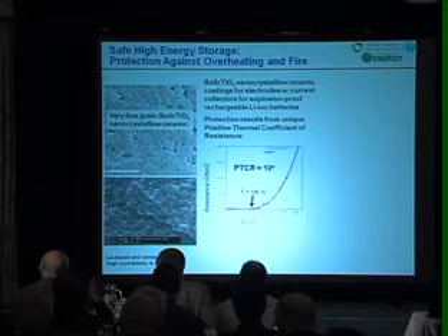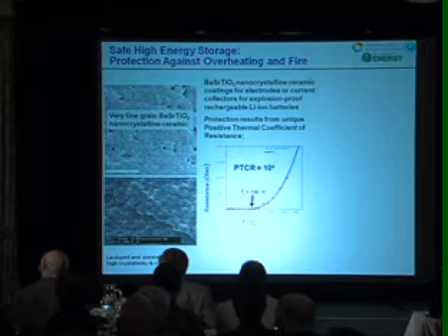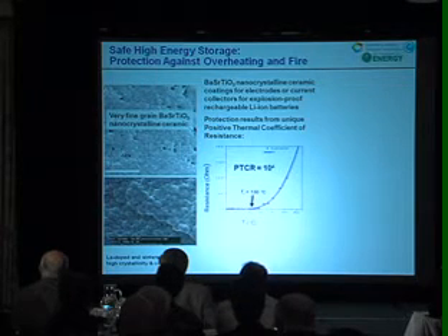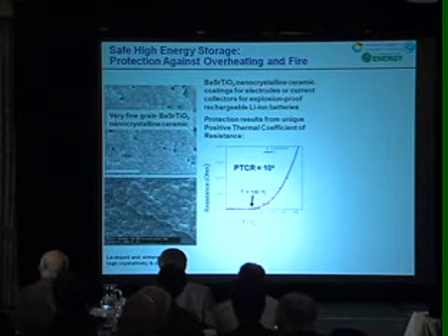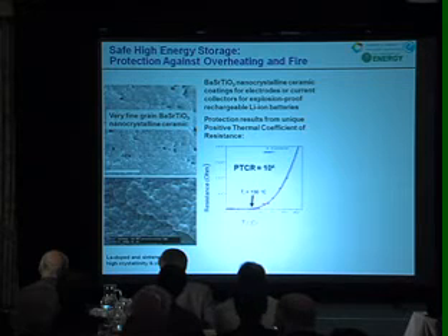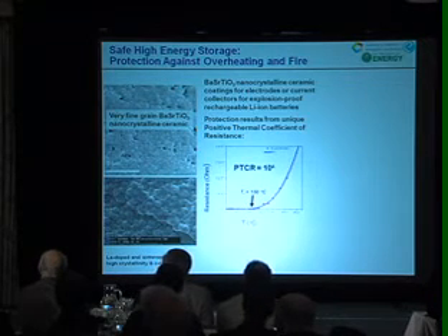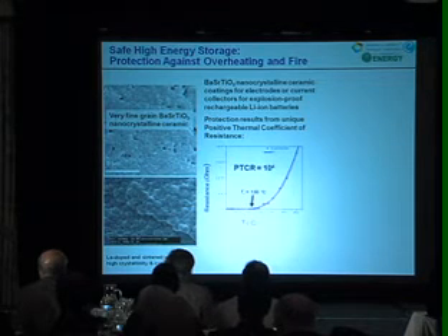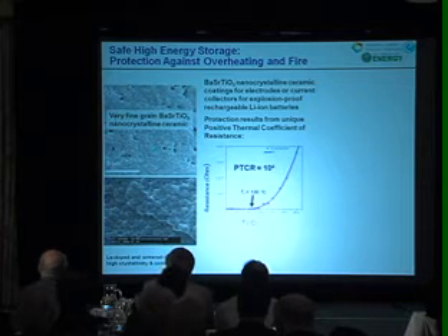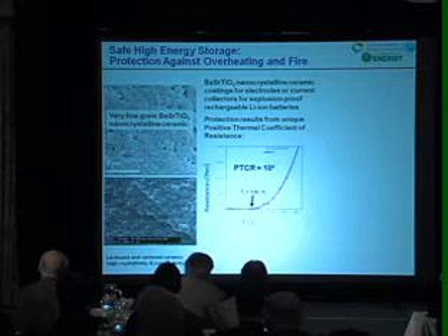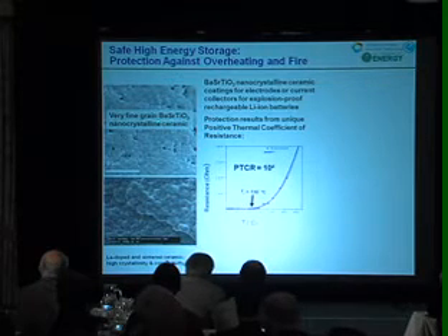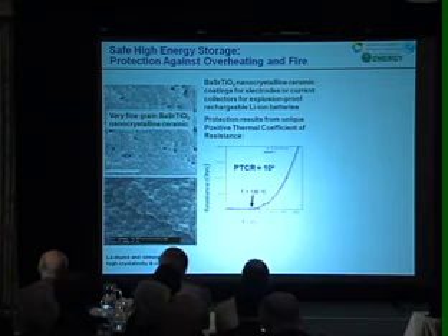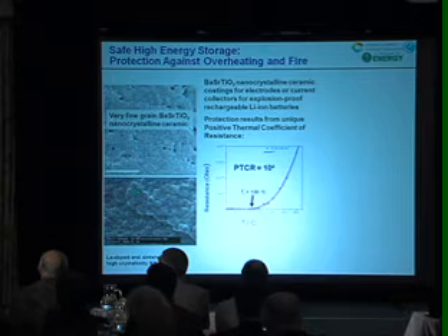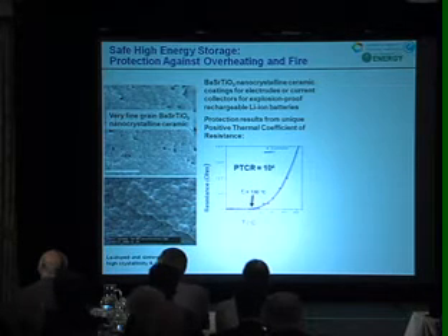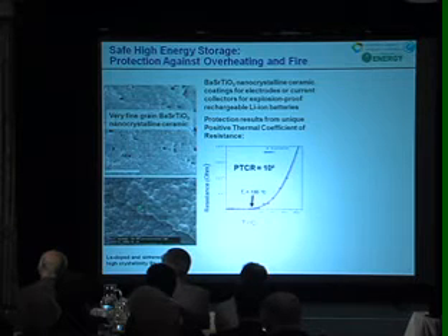I think Bill mentioned that this has been an issue for lithium-ion batteries. We're able to use this method to make amongst the world's smallest and most uniform and highest purity barium titanate and barium strontium titanate nanocrystals with exceptional crystallinity. And as a result, if we sinter, that is, cook that material, it sinters together to form a ceramic. It's like firing clay suspension to make porcelain. And here you see the retention of the very small uniform nanocrystalline grains. So we're able to make from this, by sintering, the very fine grain barium strontium titanate, which retains this high crystallinity. And when we dope it with a rare earth like lanthanum, then the material becomes highly conductive.